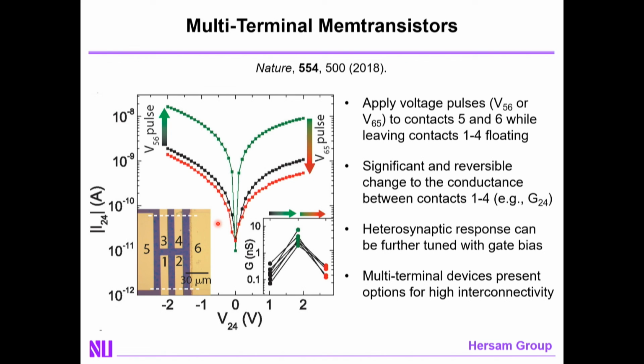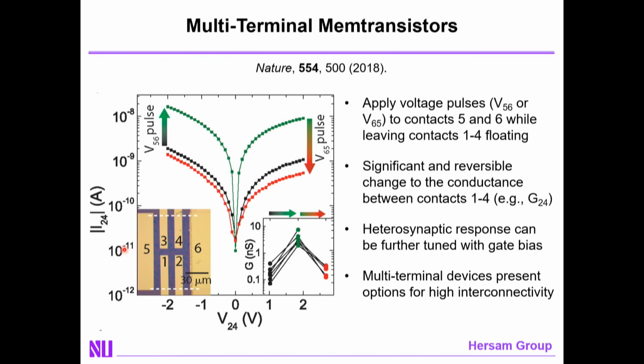Additionally, what these memtransistors allow you to do is to begin exploring the limit of higher order interconnectivity. The reason is that this is a planar device, and as a result, you're not limited to 2 contacts. You can put more contacts into the channel region. In this case, we have 6 contacts to the channel. If indeed the mechanism is that laterally applied fields are driving defect motion and therefore reconfiguring the doping profile on the channel, that should not only influence the current flow in that direction, but also in the orthogonal direction, for example, between contacts 2 and 4.